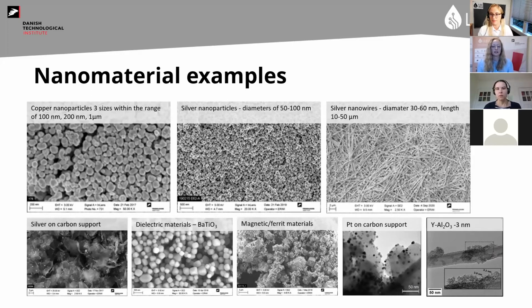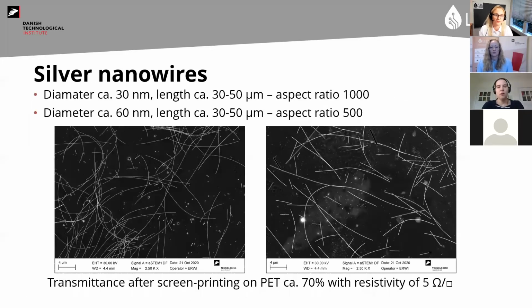And in the bottom page, you can see there are different materials that are maybe not always used for printing electronics. So the first one is from the case with the supercritical flow reactor, silver on carbon. And here you can see the nice white dots is the silver on the carbon. And we have the dielectric materials, as in the case with the autoclave, we have barium titanate. But we also worked a little bit with ferrite materials, magnetic materials. We worked a lot with platinum or platinum group metals on carbon support, mainly for fuel cell applications. And then we work with different metal oxides. And here I just have an example of a gamma alumina we produce with the supercritical flow reactor that could produce around 3 nanometer alumina particles. But I will go into some examples now.